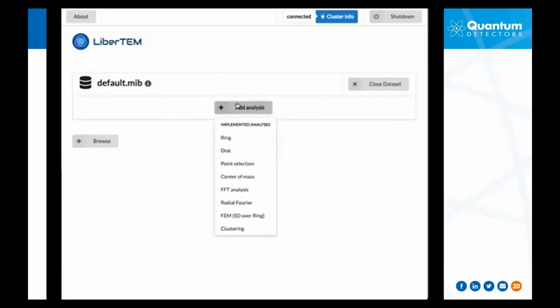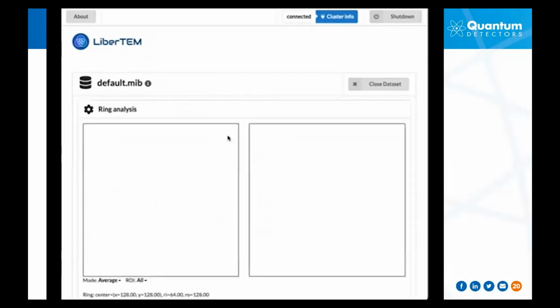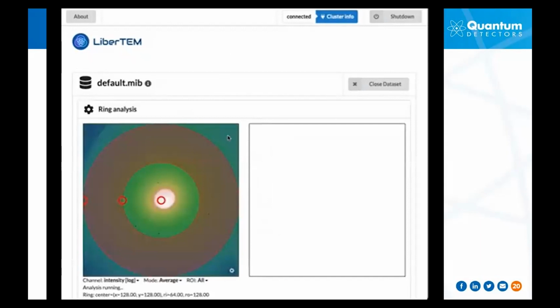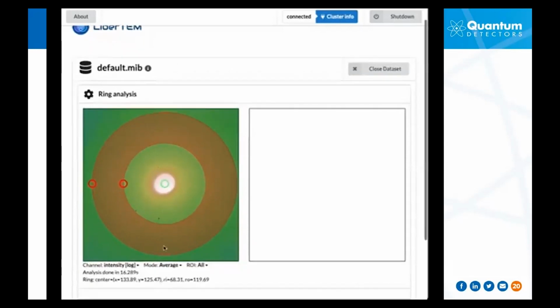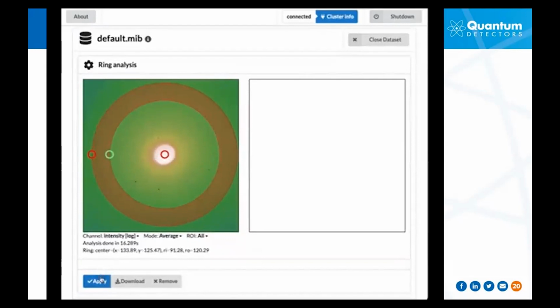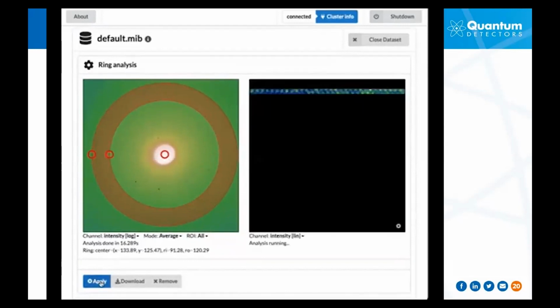Then once we click on different analysis, we have standard STEM signals available as ring or disk data, but also other more advanced algorithms. I selected the ring data here, and we can see the view of the sample. Now I select the particular angular range I want to generate the annular dark field, or in this case, high angle annular dark field image. Once I tune the geometry in the video, I click on apply, and this analyzes the data.